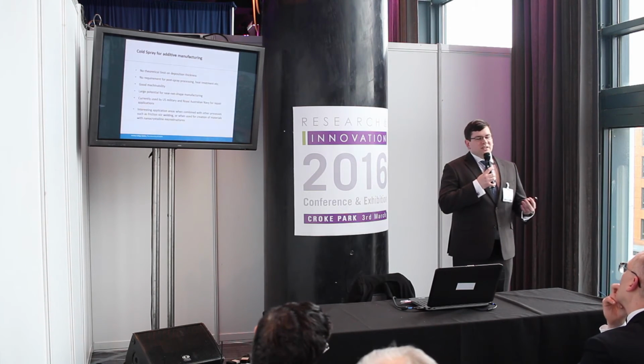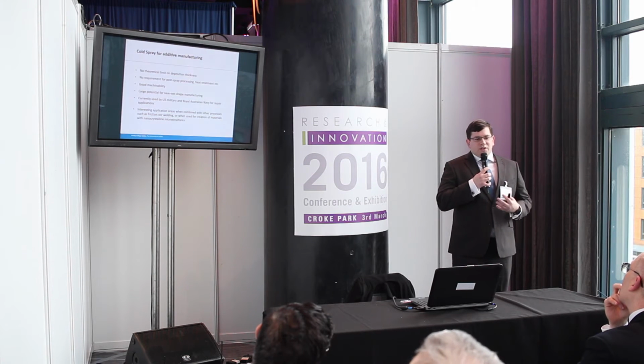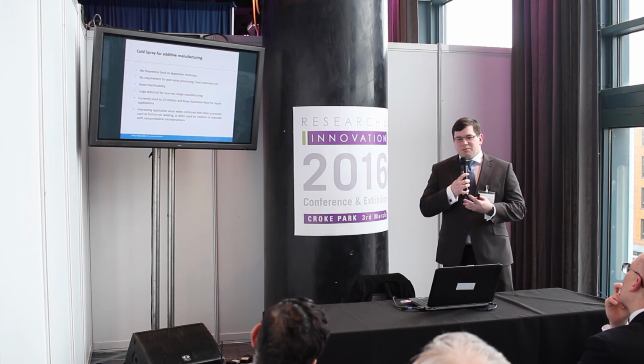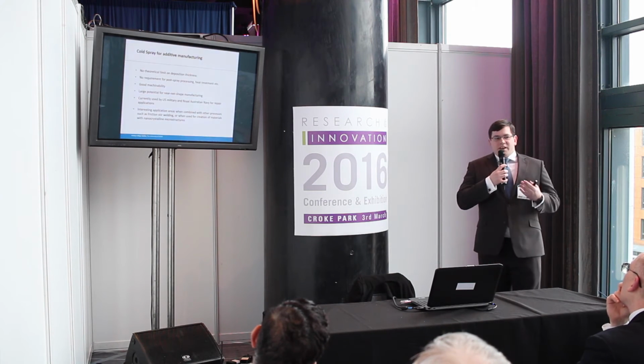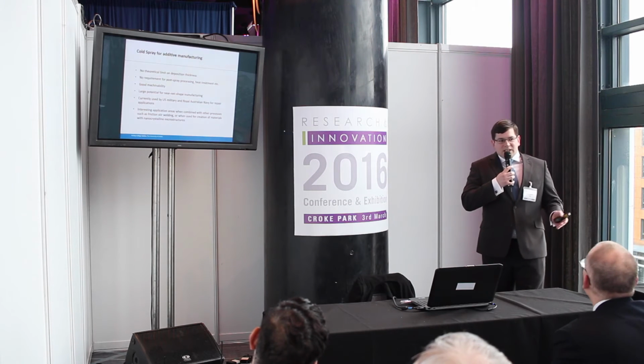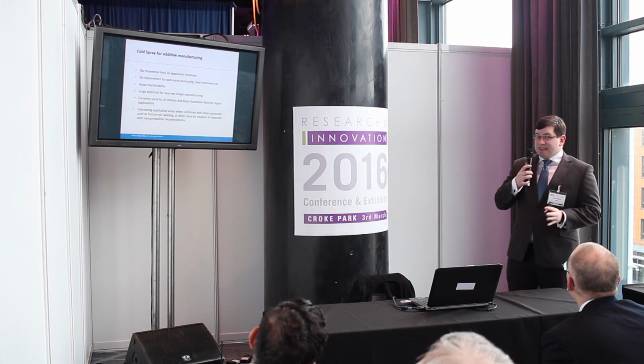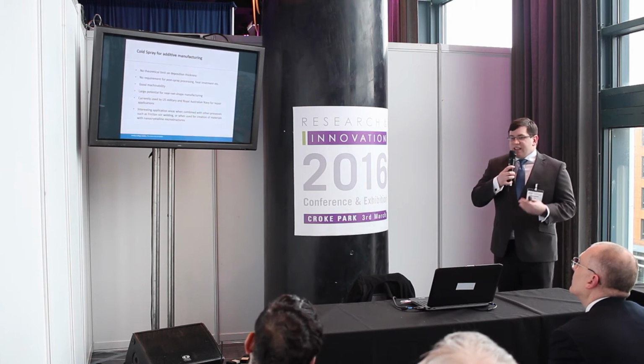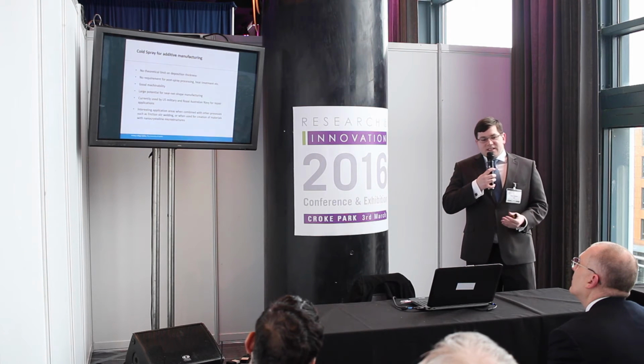So, cold spray for additive manufacturing. What I've shown you so far is very much coating based, or towards putting a coating. So cold spray is often used for hard facing or for putting a very thin layer of something onto a substrate. But why not use it for additive manufacturing? There's absolutely no theoretical limit on how thick you can make that deposit. No limit whatsoever in the theoretical way. There's no requirement for post-spray processing, heat treatment, etc. You can do heat treatment processes, you can improve various properties, but you don't have to do it.